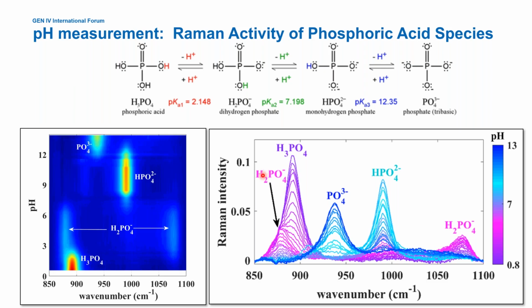As we deprotonate, we go to the diprotic form, the monoprotic form, and then the fully deprotonated tribasic form of phosphate. And just an overhead view of that same spectra as a function of pH, you can see quite visually the phosphoric acid bands, the diprotic form, the monoprotic form, and then the fully deprotonated form. And we can use this data as a training set.